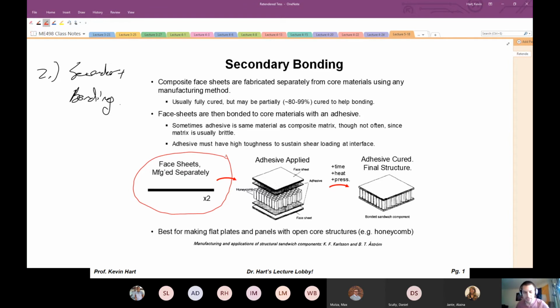All right. So you manufacture these face sheets separately, and then you apply an adhesive between the cured face sheets and what will be your core. So here we have a honeycomb core, for example. And then with additional time, heat, and pressure to cure the adhesive between the two, you end up with your final sandwich structure, which looks like this. A majority of sandwich composites are actually made this way. So I would say most of them are made in this method, though co-curing is also right up there.